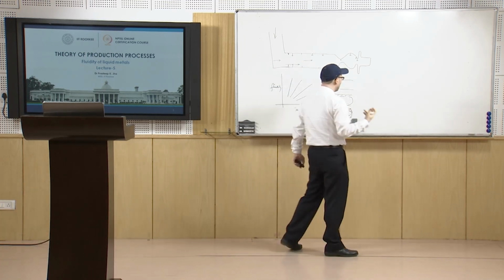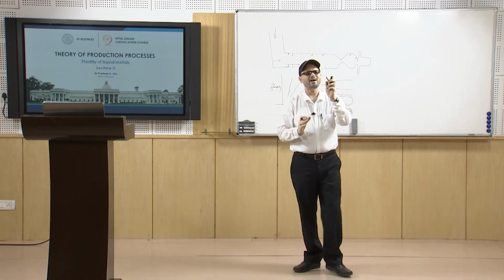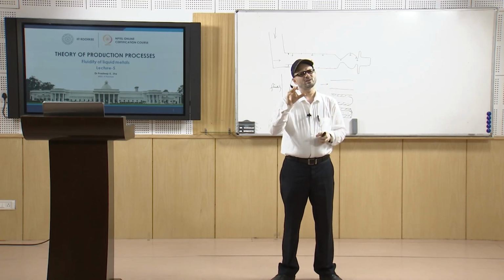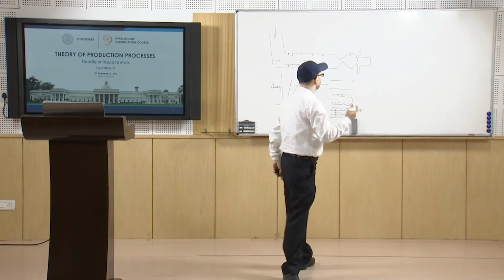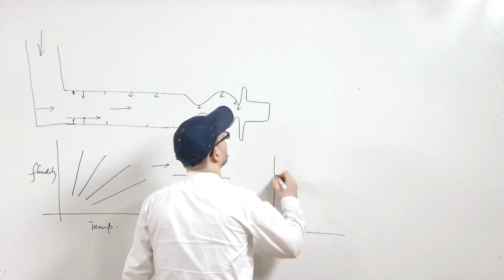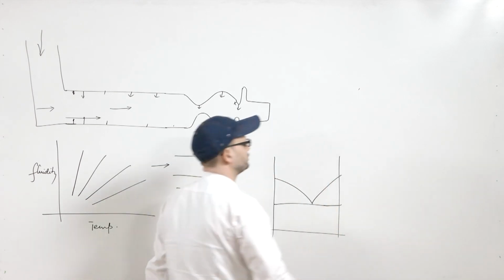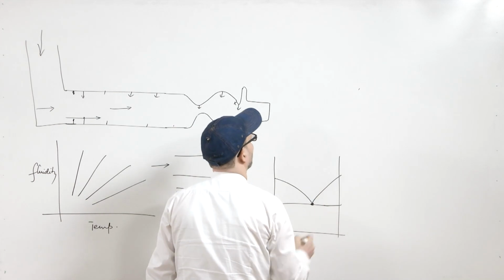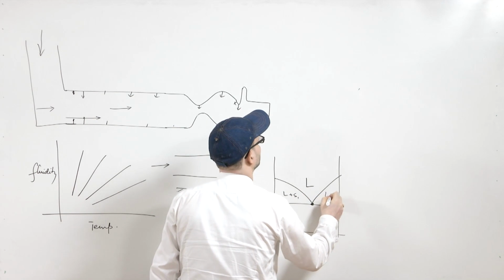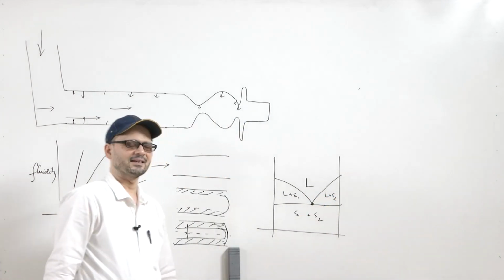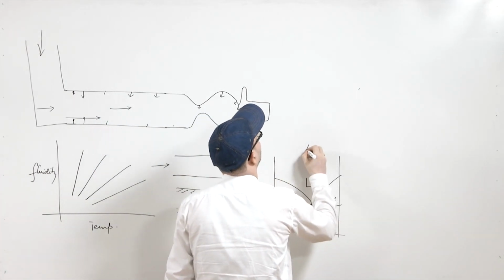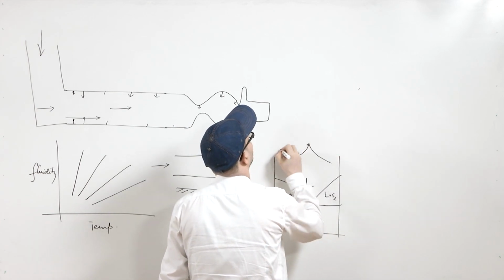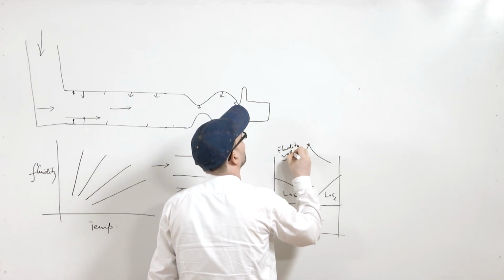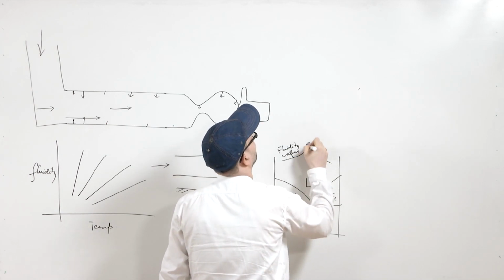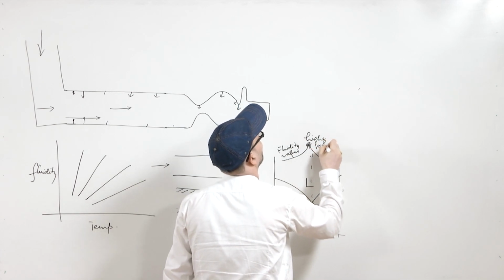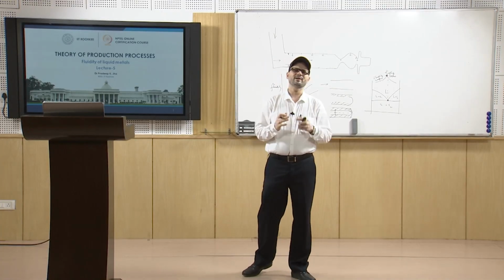It has been seen that metals which solidify at a constant temperature, either pure metals or metals with eutectic composition, have higher fluidity. So, when the fluidity test was carried out, suppose you have a two phase diagram like this. This is known as the eutectic point, where this is liquid, and this is liquid plus solid 1, liquid plus solid 2, and this is solid 1 plus solid 2. In that case, you see the fluidity will be higher here. So, this will be the fluidity values. At this point of eutectics, you will have a higher value. That is why in case of such metals you will have larger fluidity.